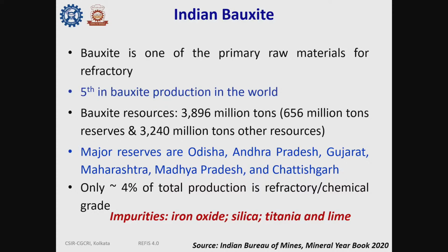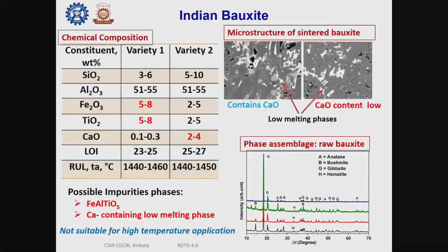However, the problem is that out of the total production, only 4% is either refractory grade or chemical grade. The impurities present are primarily iron oxide, silica, titania, and lime. And broadly, we can categorize refractory grade bauxite into two groups. One is where iron and titania are present, and the other is where CaO is also present. And the presence of these impurities dictates the low melting phases formed in the bauxites.